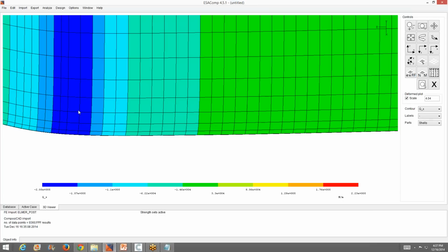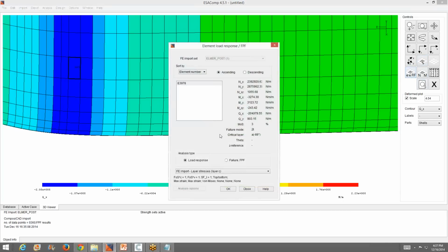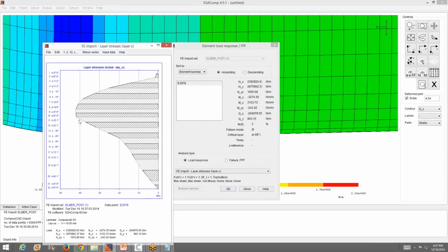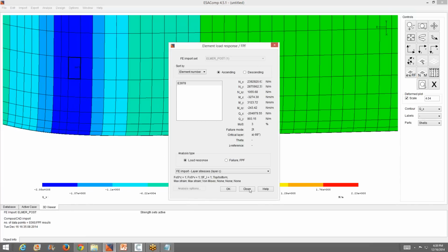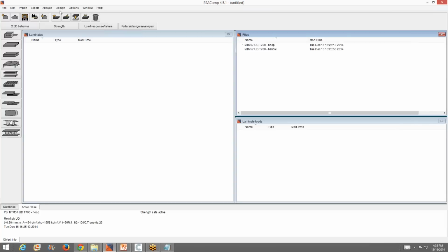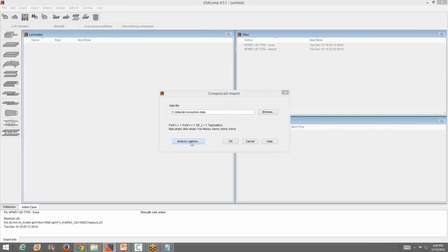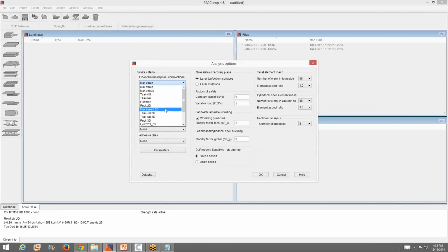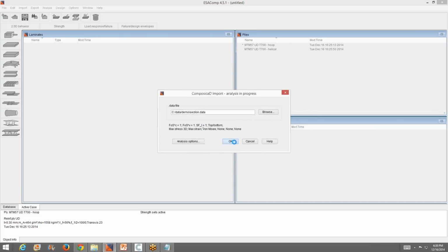So this gives you a nice overview where you have an oscillation of the result items. So in this region, QX has a high peak, and I will go to the peak element from that region. And I study locally that one, and it's over 40 MPa. Actually, that wasn't straightforward to find that critical region from the model. So I will go once more back, and I will change the analysis options so that also the out-of-plane is considered. One possible way is to select max stress 3D failure criteria and repeat the analysis. And waiting the results.